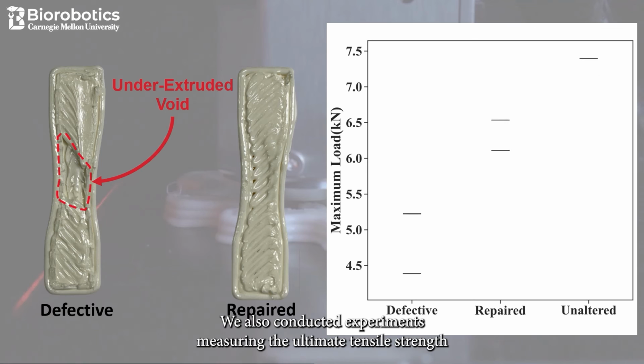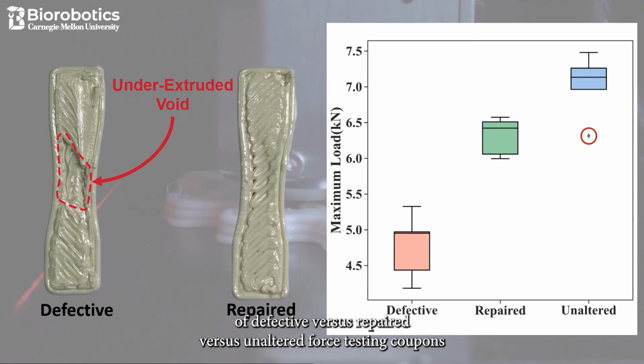Further, we also conducted experiments measuring the ultimate tensile strength of defective versus repaired versus unaltered force testing coupons, where we see that the repaired coupon's maximum load is much higher than the defective parts.